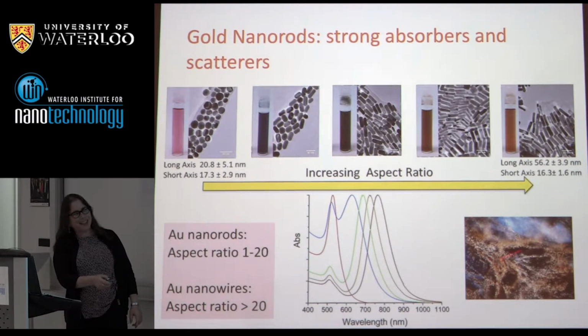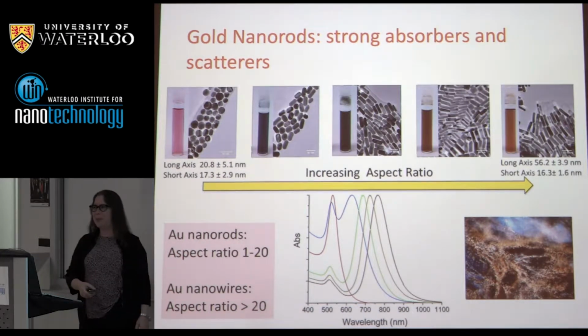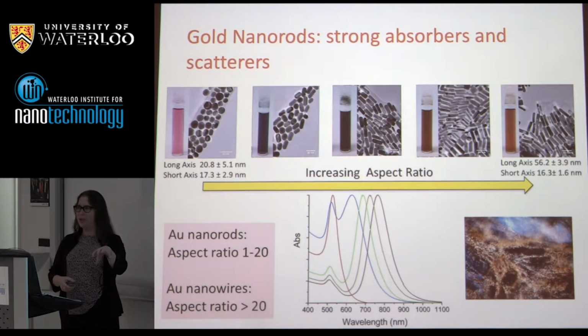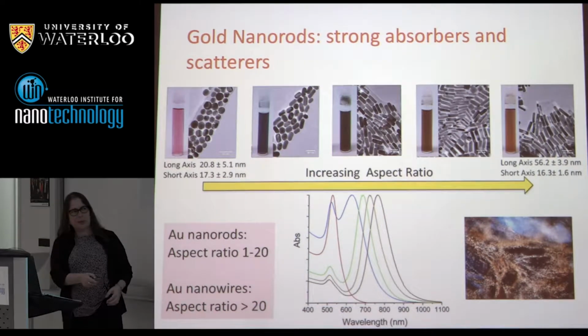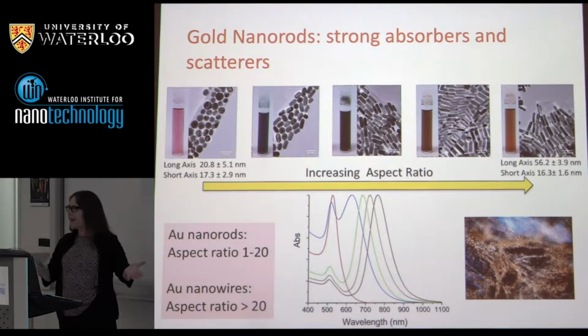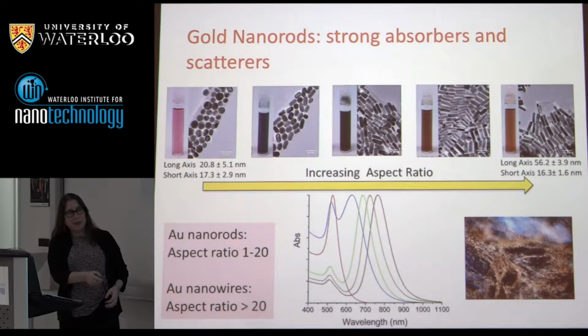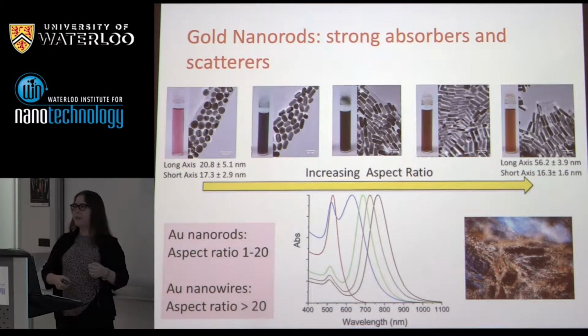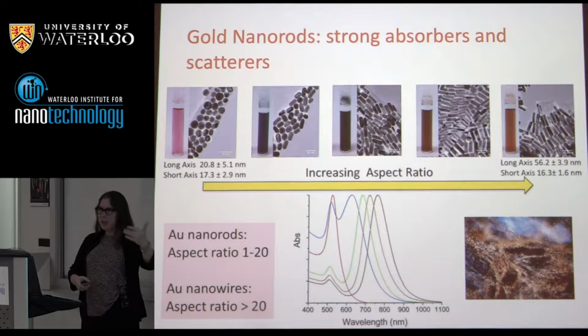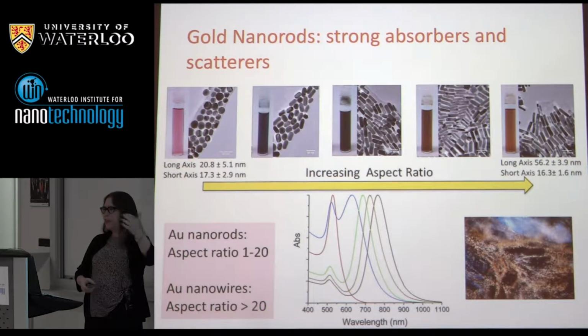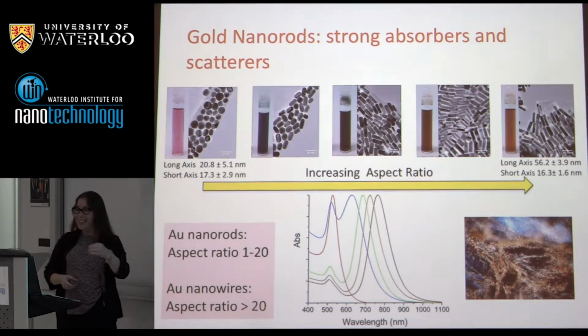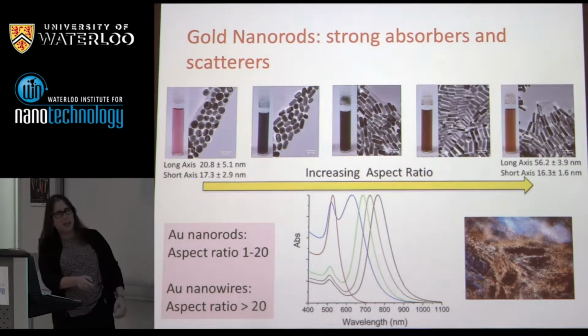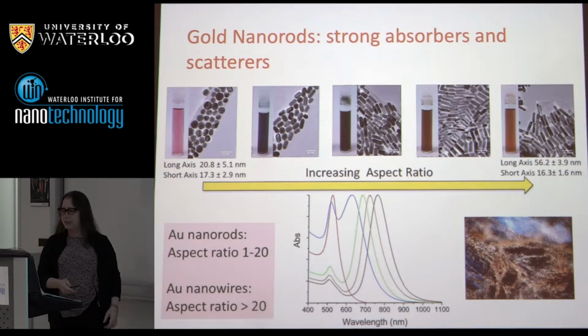So this little picture here looks like a galaxy. If I told you it was a galaxy, you'd probably believe me, but what it actually is, it's a dark field optical micrograph of our nanorods immobilized in a polymer gel. So all we're doing in this experiment is we're sending white light into the gel, and we're just collecting light that's scattered out to the side. So it's just Rayleigh elastic light scattering, why the sky is blue kind of scattering. So the field of view is about 3 millimeters, but all the little stars in the sky, those are the particles. So that's not an absorption and a re-emission of light, it's just a scattering event. So there's no bleaching, there's no blinking, and you can follow them around even in a turbid matrix like this polymer gel, which gives rise to these kind of misty colors we see here.